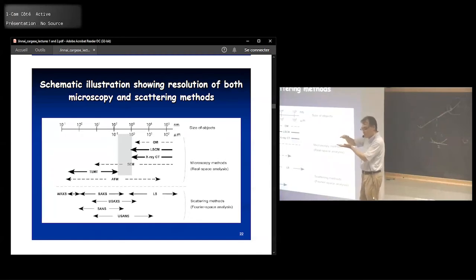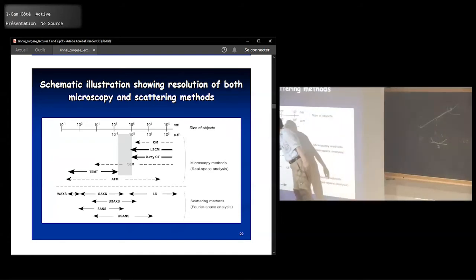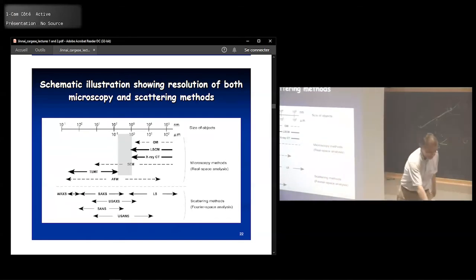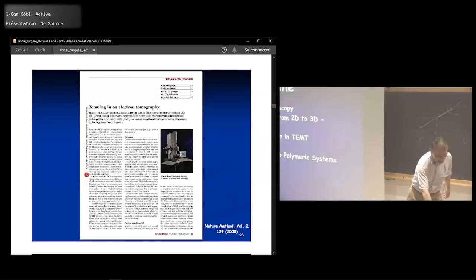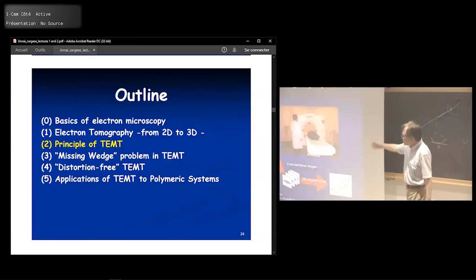But for three-dimensional imaging, a thinner sample to visualize in 3D, that's not very impressive, right? So we increase the thickness of the sample, like 150. Then the transmittance is getting lower, and then, like I will explain later, we tilt the sample to do the imaging. So the cutoff is somewhere here. Okay. So the principle is here.